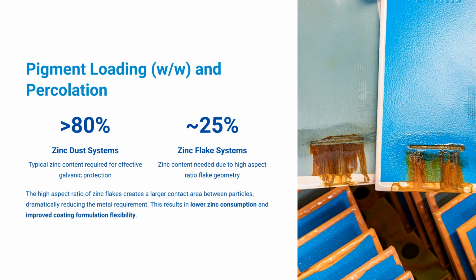The difference in percolation threshold directly impacts required pigment loading. Conventional zinc dust systems typically require more than 80% zinc content to establish sufficient conductivity. Zinc flake systems, however, can achieve effective galvanic protection at approximately 25% zinc loading. This reduction is possible because the high aspect ratio flakes create much larger particle contact areas. Lower zinc loading provides several important advantages, including reduced raw material consumption, improved formulation flexibility, better overall technical properties, and